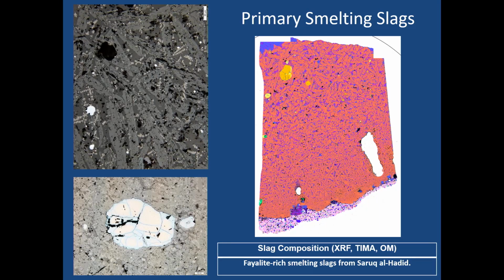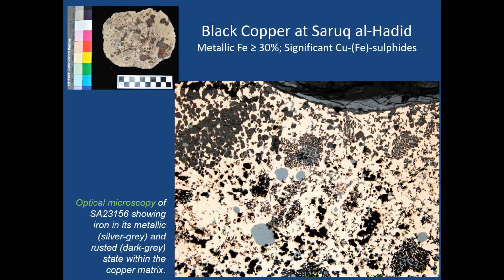So we've got analyses of primary smelting slag, which tell us about the nature of the ores that were being used at the site and some of the temperatures that they were reaching. You can see on the lower left-hand side a large piece of ore which is semi-reacted and still included in the slag, which is telling us they're processing sulfide ores. And in particular, we can look at the metal that they were producing at the site, and we can see that they were struggling. They were producing metal that was very, very full of impurities.